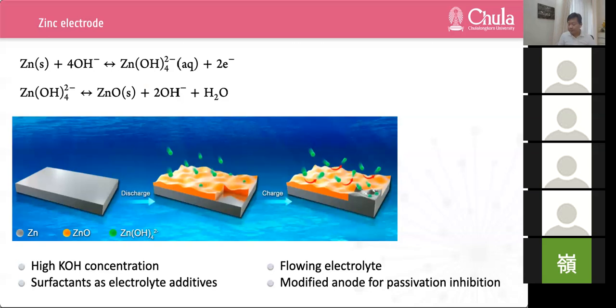And the next approach is to use modified anode for passivation inhibition. The development of modified metal anodes is an effective means to improve the capacity and rechargeability of batteries. The preparation of modified anode includes the tuning of the zinc anode structure and surface modification of the anode particles. Tuning the zinc anode structure refers to development of porous active anode material with high surface area. And surface modification of the nano-sized anode particles refer to cladding zinc anode particles with various ion-sieving nanoshells.